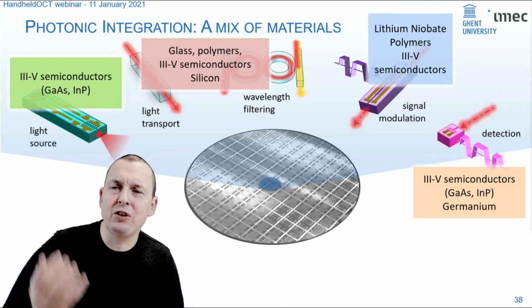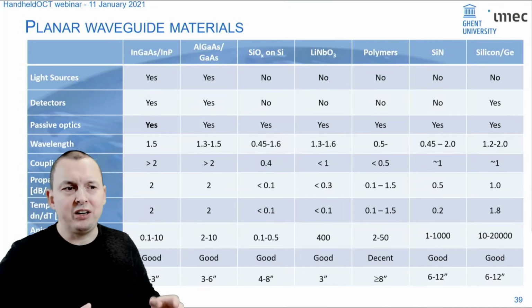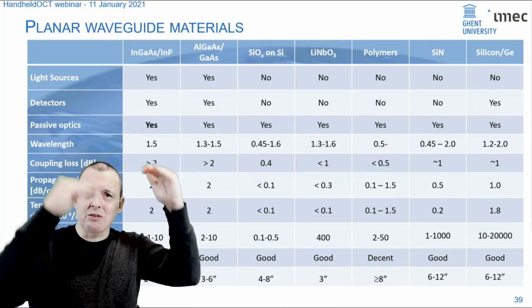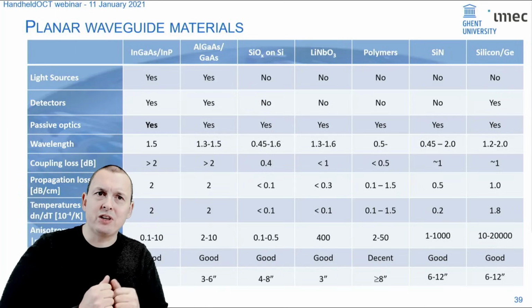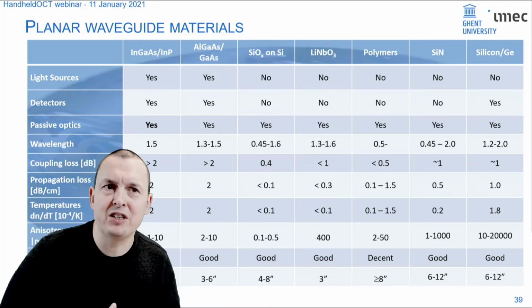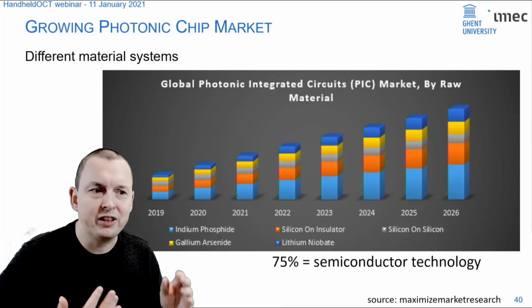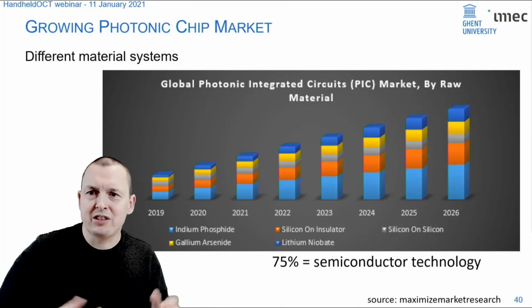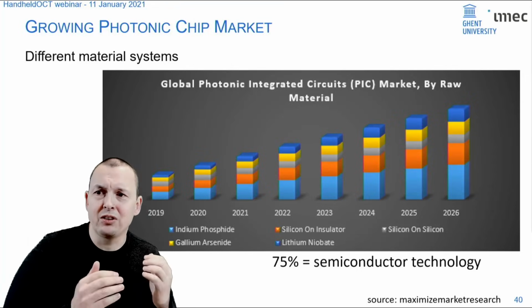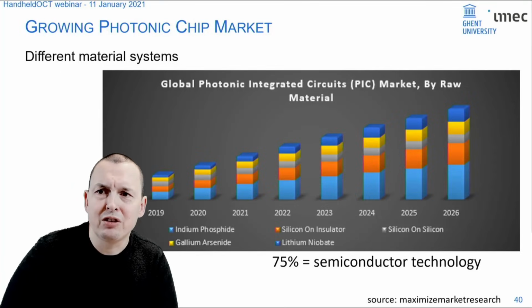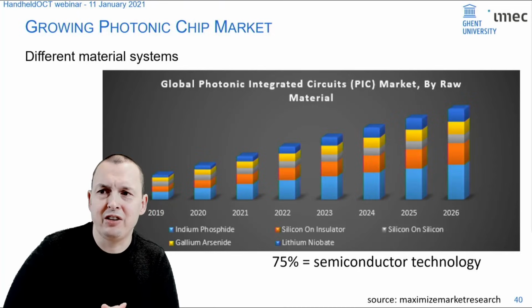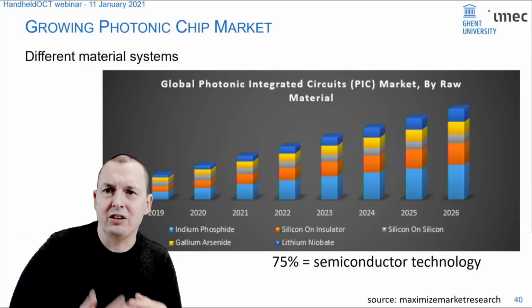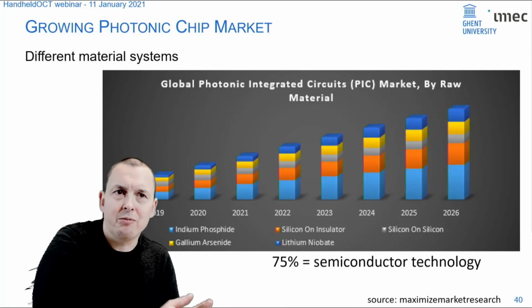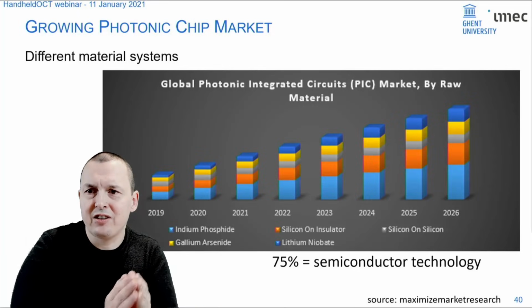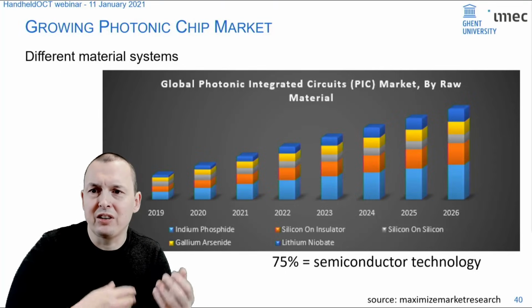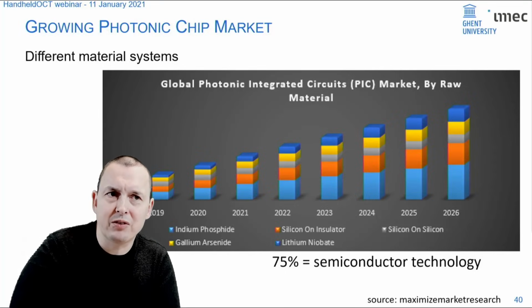So that means that if we look at the landscape of photonic integrated circuits, we have a table like this where you can set off all your different material systems and look at all the pros and cons, and you will find that they all have their strengths and weaknesses. And that's why if we look at the photonic integrated circuit market today, we see that it's still quite largely fragmented. We have a large section, actually the majority of the photonic integrated circuits today are still indium phosphide, so III-V semiconductor. But depending on the wavelength, you might prefer gallium arsenide. Now you also see that there's silicon, there's lithium niobate, there's silica on silicon. So there's a lot of different material systems that can be used.